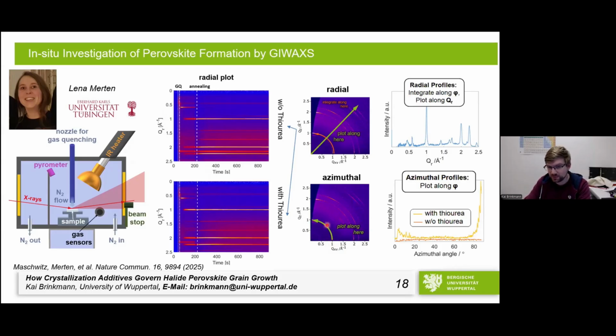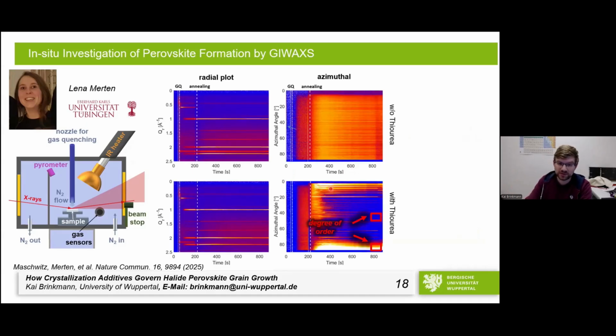So what we did is we probed along the radial axis here, and along the azimuthal axis. And this azimuthal axis basically gives you the orientation. So basically this point here versus this point here gives us a measure of the orientation. So we can finally probe when during the perovskite deposition, we actually end up with larger and more well-oriented grains. And if we do this, we see something that at least surprised us quite a bit.